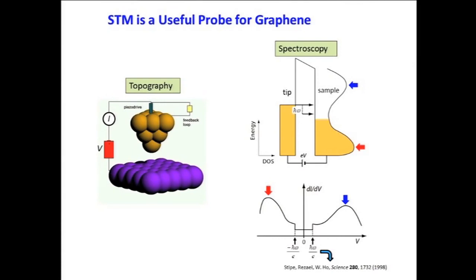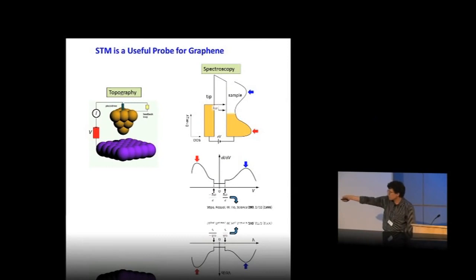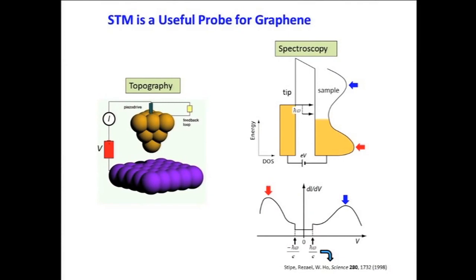And this is a very useful quantitative measure because the electronic local density of states gives you a measure of the probability of finding an electron at a certain point in space at a certain point in energy. So if you can map that quantity out, you can learn a lot about what the electrons are doing in small structures. Also, by varying this voltage and measuring the differential conductivity of this STM tunnel junction, you can measure what we refer to as dI/dV. And by measuring that as a function of the voltage between the tip and the sample, we can measure the energy dependence of the local density of states beneath the STM tip. And that's what this little cartoon is meant to show. And here, V equals zero is the Fermi level, and these are filled states, and these are empty states.